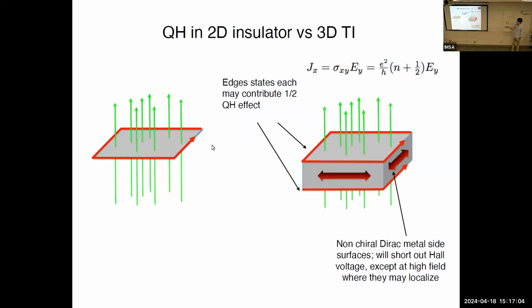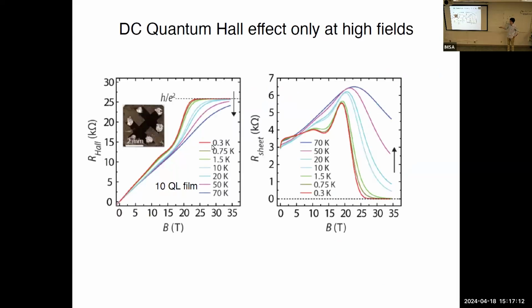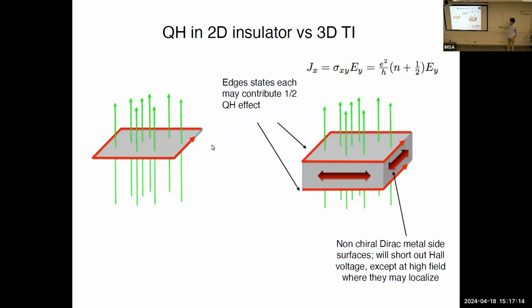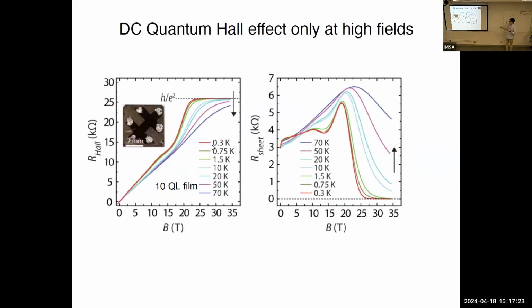So if you were to put probes on this 3D-TI and try to measure the Hall conductance, you won't be able to do it with small magnetic fields, because whenever you put the contacts, this non-chiral edge state may just short your voltage measurements, and you won't be able to see any Hall effect unless you apply a gigantic magnetic field, which in this case is about 25 Tesla.